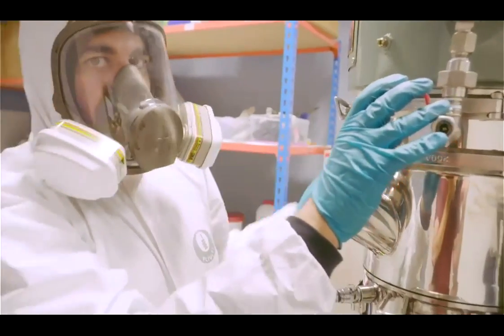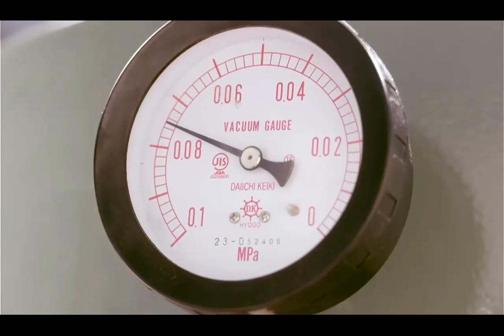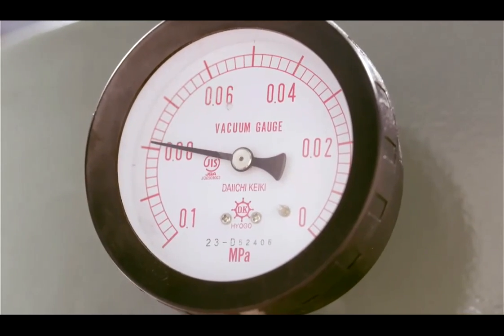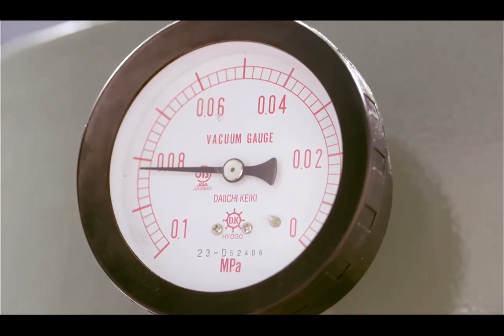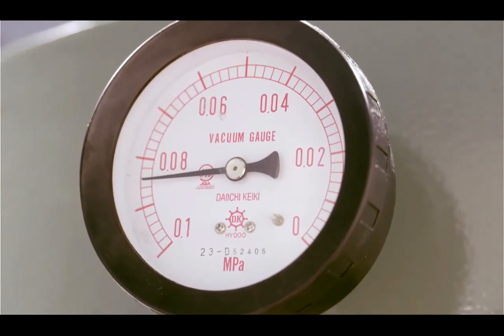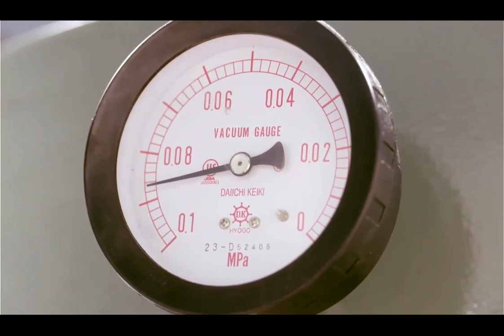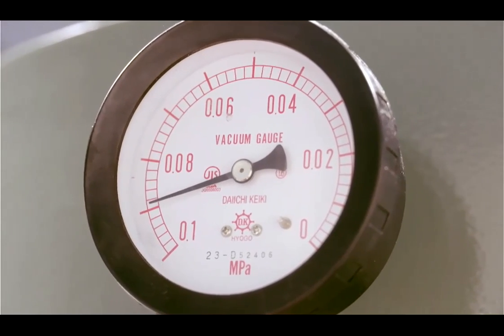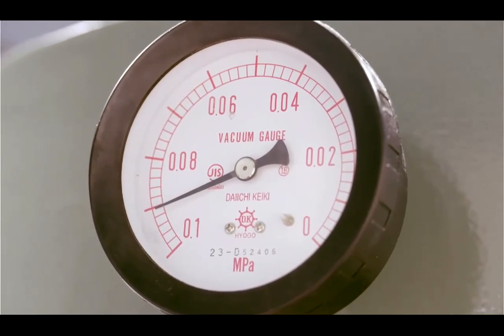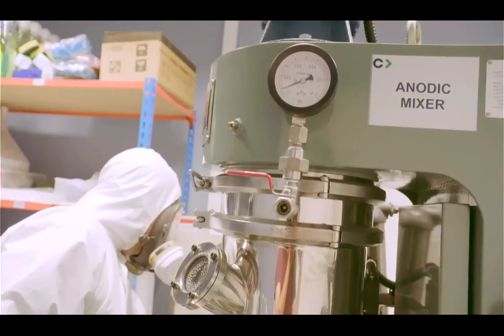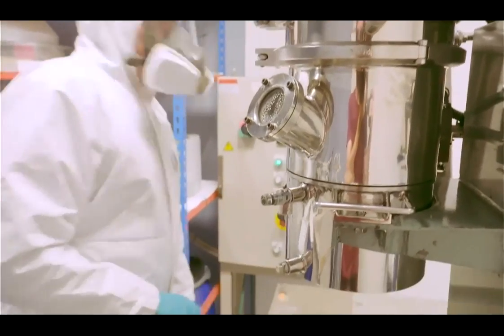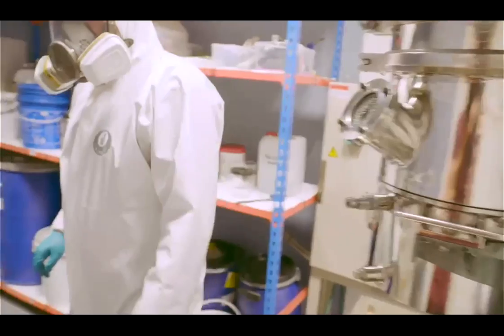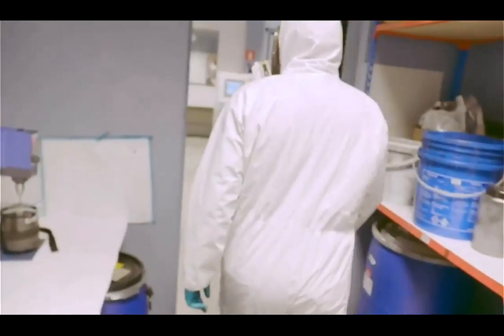Sometimes, when you are optimizing the mixing procedure, you need to include a step where you are using high shear. This provokes some bubbles in the slurry. So with this type of mixer, we have the possibility to apply vacuum and get rid of all the bubbles that we have generated in the slurry.